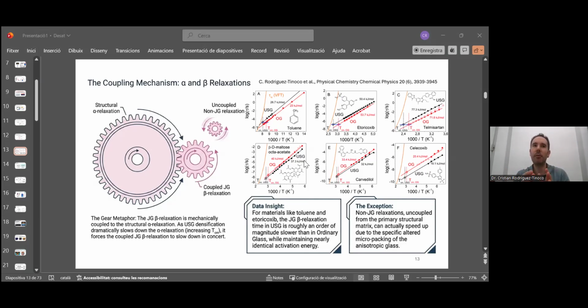Let's say that the glass is formed by clusters of molecules, and in between these clusters, we have some kind of regions which can have higher density, no? In the case of the ultrastable glass. So it's somehow related to some kind also of dynamical heterogeneity in the glass, no? So the thing is that we can use this difference in behavior between one kind of relaxation and the other, to know the nature of the particular relaxation process, okay?